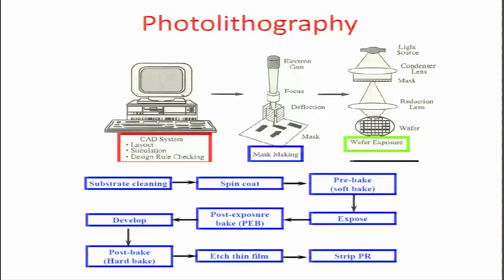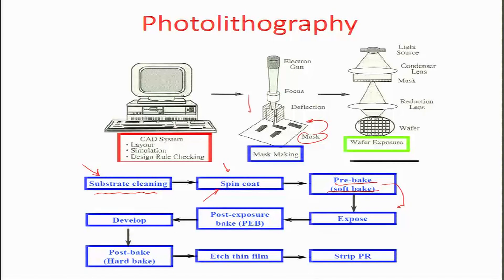Lithography starts with a cleaning step where a silicon substrate is taken and cleaned through various cleaning protocols to remove all organics and other contamination from the surface. After substrate cleaning, you take photoresist and spin coat it on the wafer, creating a thin layer of photoresist film. You then pre-bake or soft-bake the film to remove all moisture content, and then expose the pre-baked film to a certain wavelength of light using a well-defined mask in the beam path.